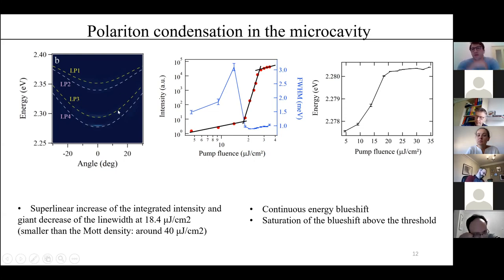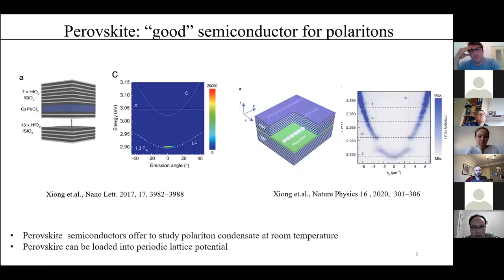I don't know. In our case, we think the mechanism for the polariton condensation is the same as other semiconductors like gallium arsenide. Do you think the same mechanism? Yeah, I think so. Because the advantage of this material is the binding energy and oscillator strength of the exciton is very large compared with other materials. So we can see condensation at room temperature much more easily. Like in this work, they also observe condensation of similar perovskites. I think it's the same.